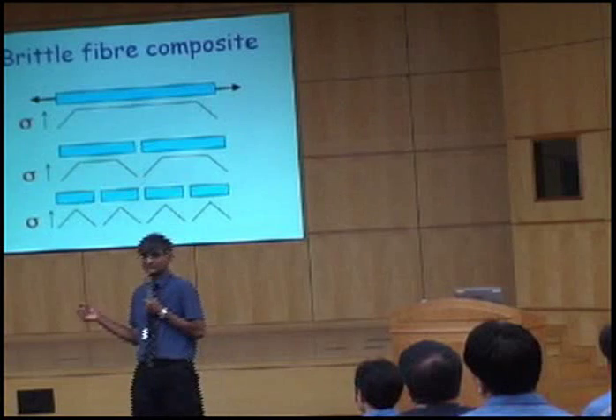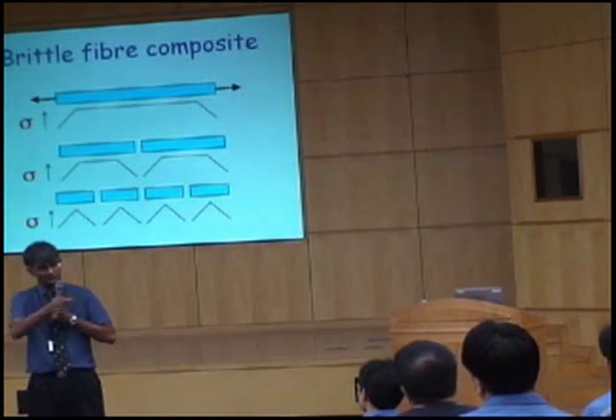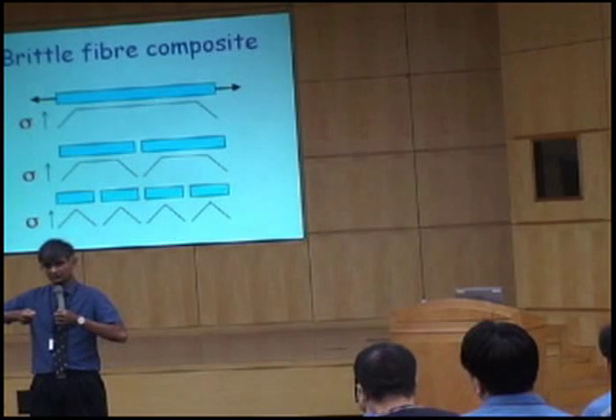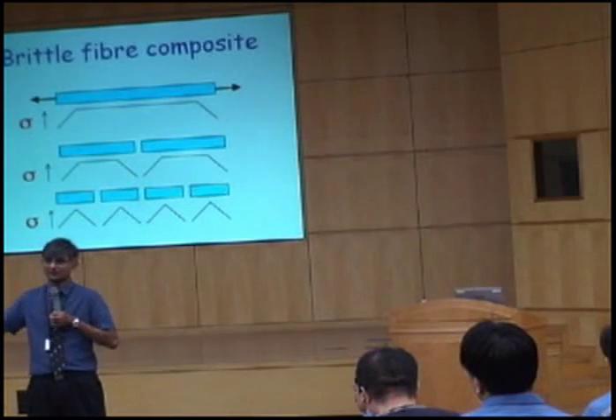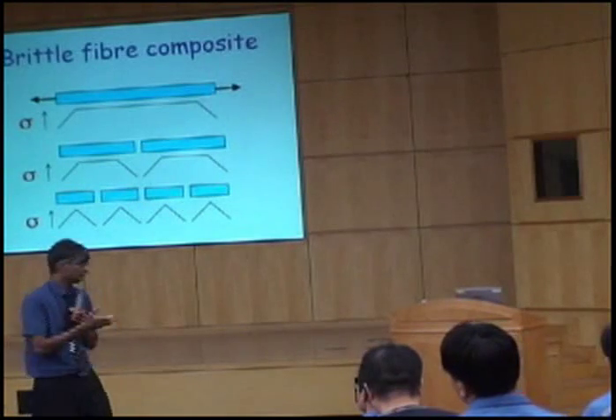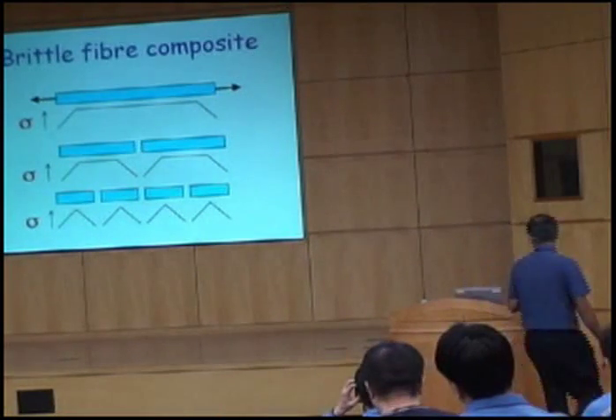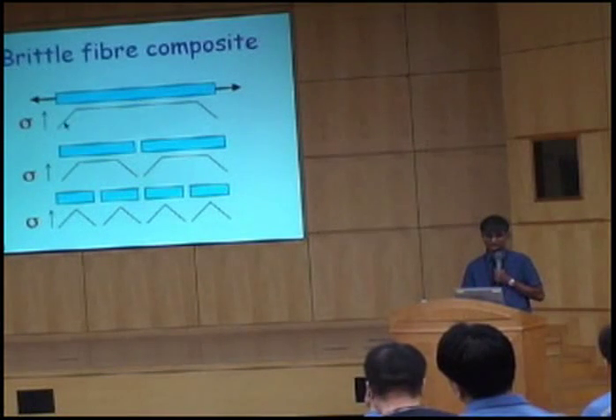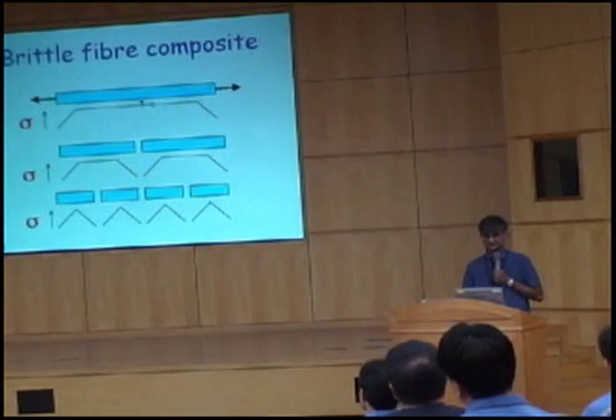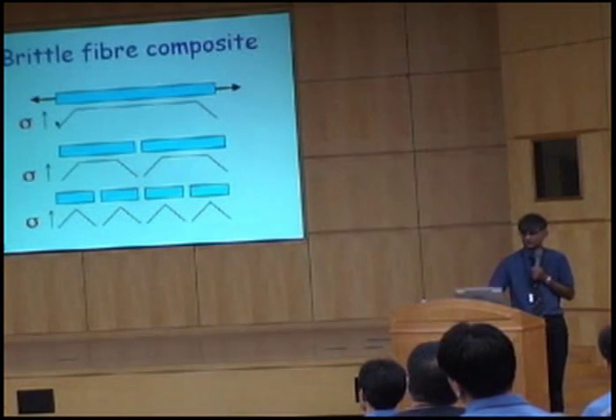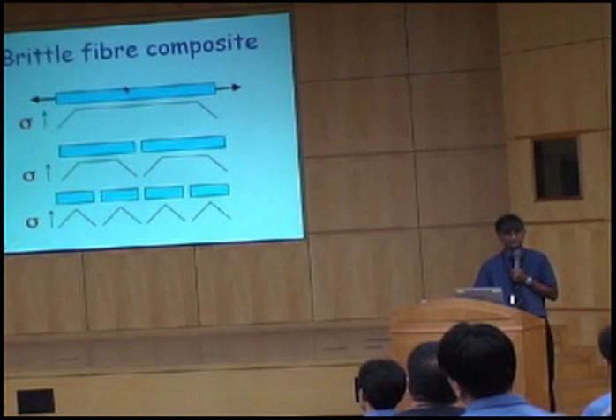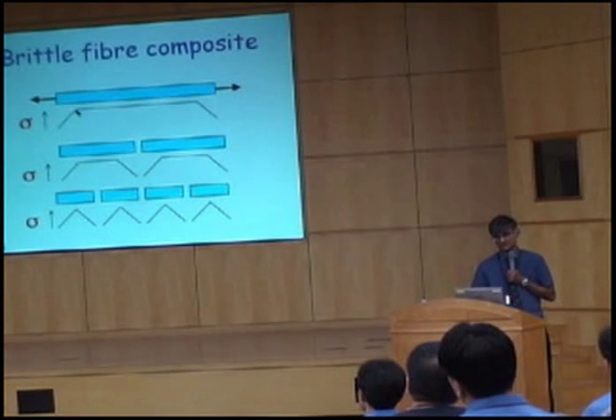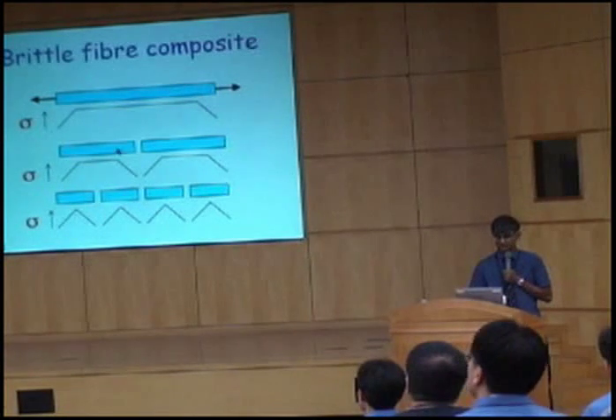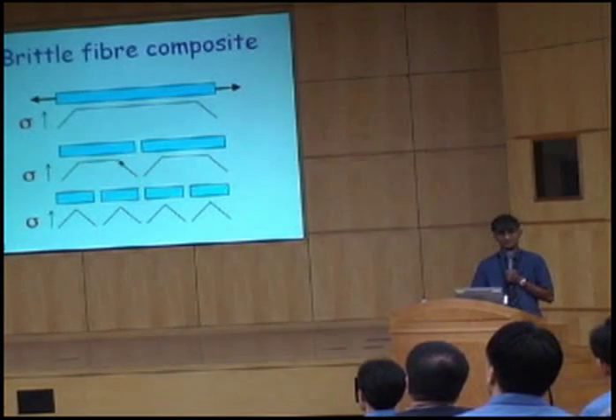So for example, glass fiber inside a polymer matrix. We make long fibers of glass inside polymer. When we pull the composite, the glass fiber will crack because it's brittle. And the distribution of stress on that glass fiber is like this. The ends experience less stress than the middle because you have to transfer the stress from the polymer to the glass through the interface. And here there is a weaker transfer, so you have to build up the stress, a uniform stress in the middle and less stress at the ends. So when you pull it, it will break into two bits and the stress distribution inside the glass changes like this.